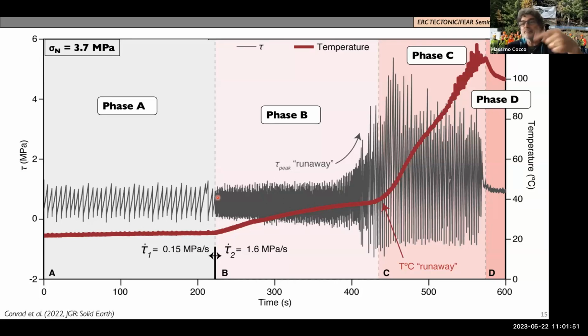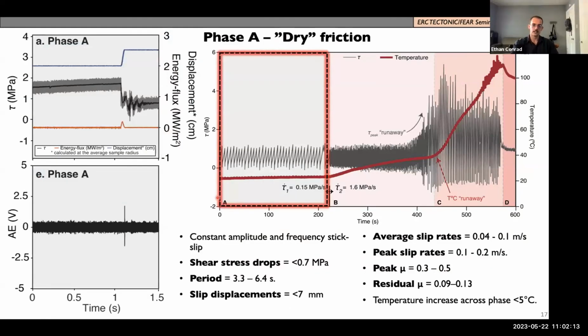So this means that you have a sort of stationary properties, because in a rotary, you do not preserve the initial condition of the interface. The interface is always perturbed. This means that you have a sort of steady state interface features that you maintain over multiple rotary experiments. Exactly. So over multiple events, you have relatively regular behavior until we change the loading rate. We haven't experimented through this, but this supposedly could occur indefinitely, that the interface reaches some kind of steady state effectively, and then the amplitude or the peak friction doesn't increase. Everything remains relatively uniform. Thanks. Now I understood, and I will be quiet.